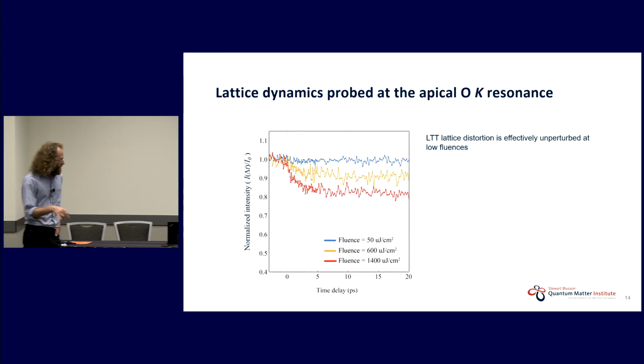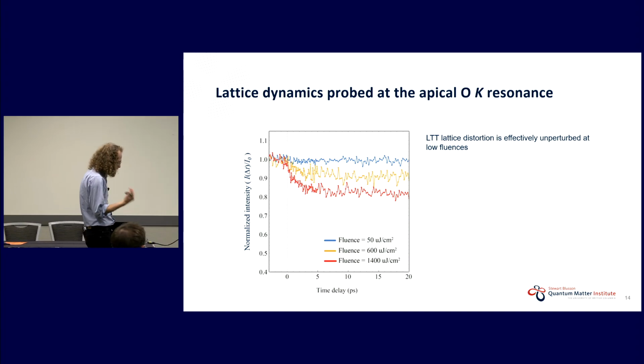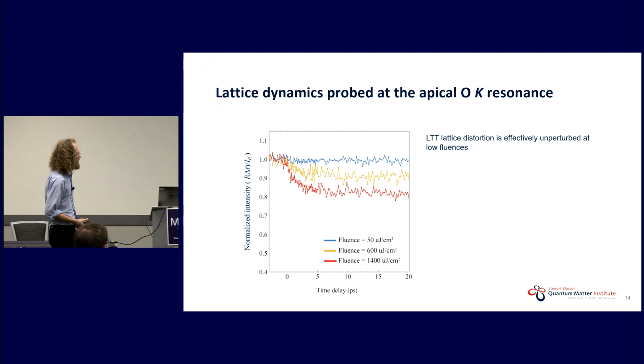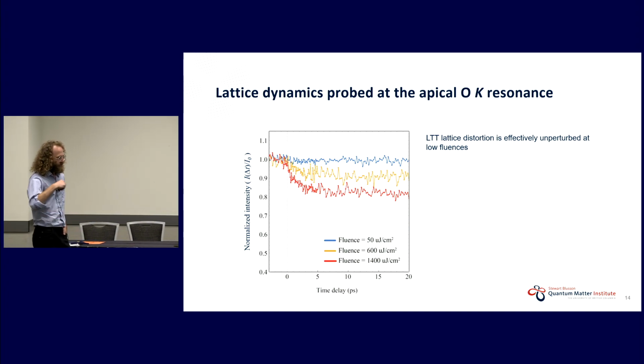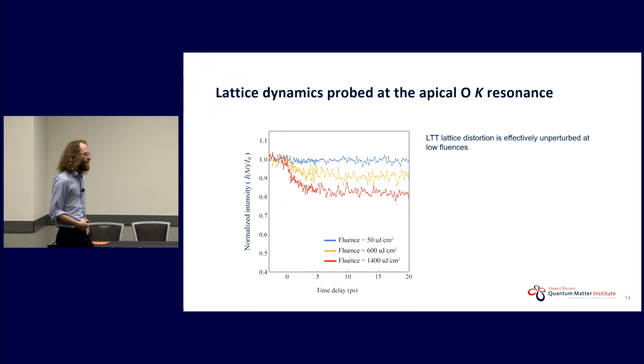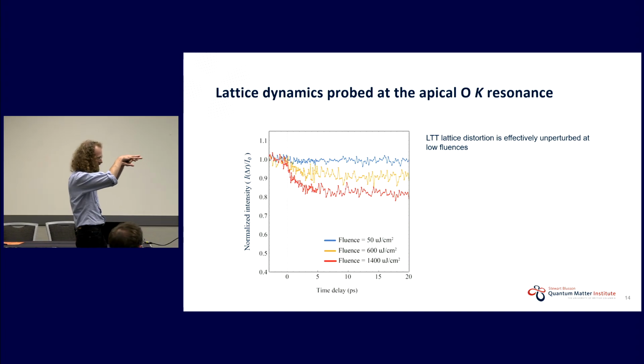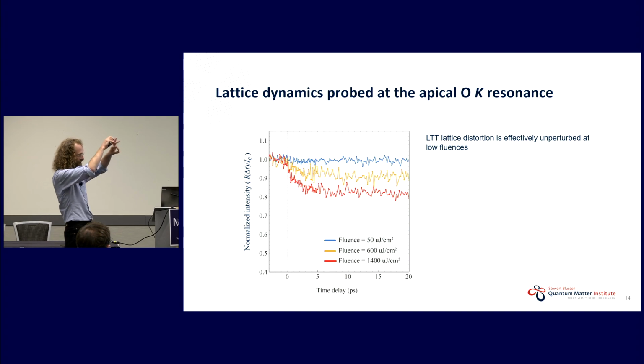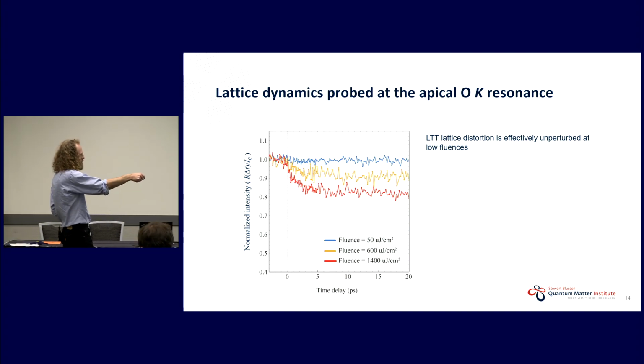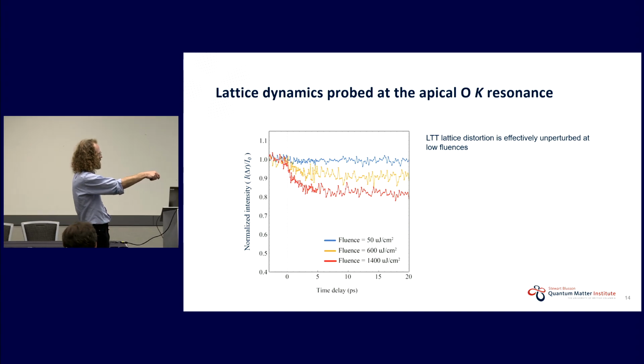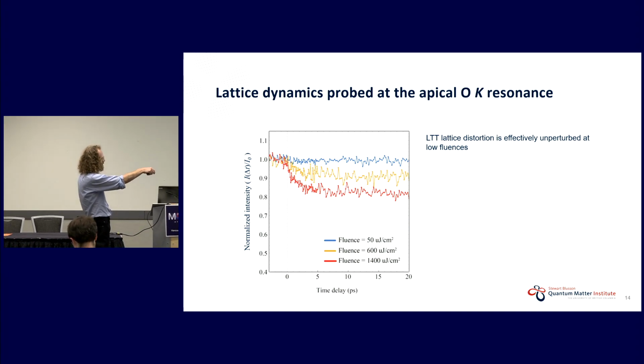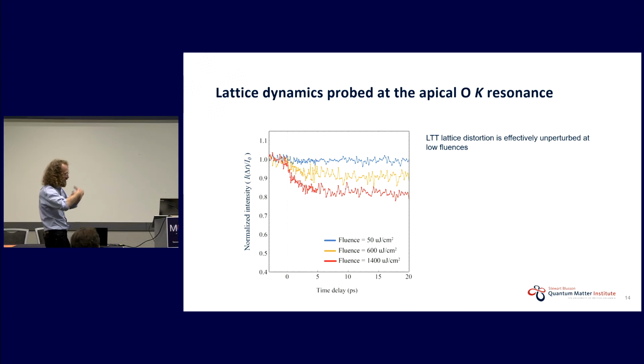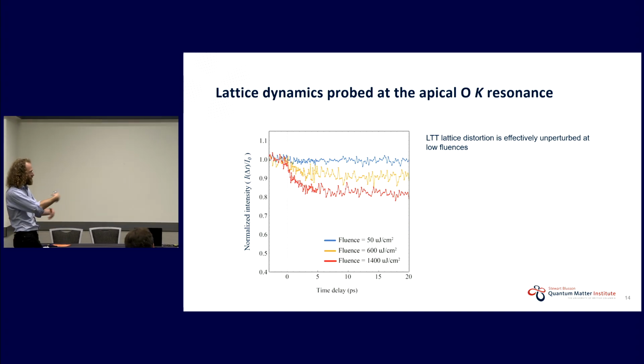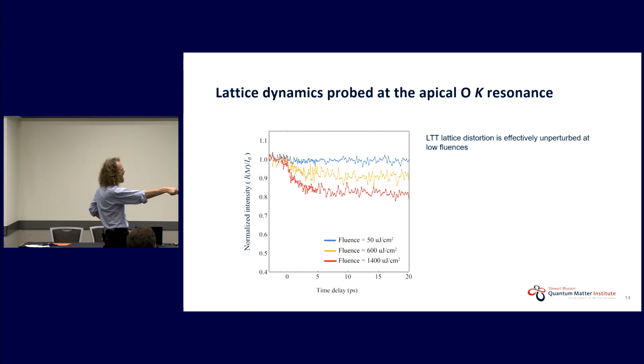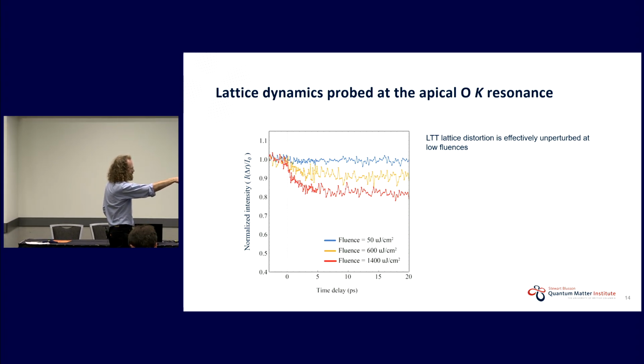Okay, so the first thing that we want to do is we want to establish what are the dynamics of the structure, okay? So the way we're going to do this again is we're going to start by studying at the apical oxygen K resonance, where we know that we're just seeing the effect of the LTT distortion on the lanthanum oxide layer. And we do time delay curves as a function of fluence, okay? So at high fluences, you can see that, over a couple of picoseconds, this hot quasi-particle population that you excite with the pump couples via electron-phonon coupling to the lattice, and you start to get a suppression of the LTT peak, which doesn't recover for maybe hundreds of picoseconds, okay?